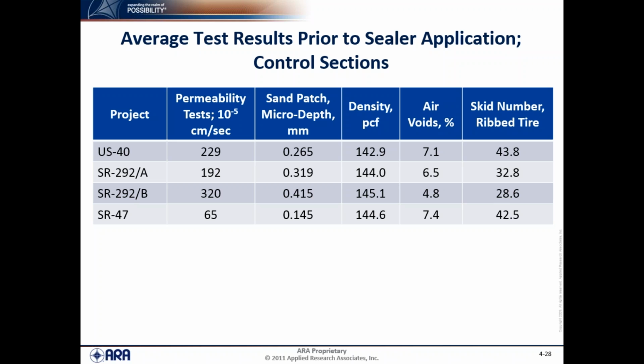So permeability, and you're going to see later on, there was a lot of variability in the water-based field permeability test. And you'll see that in some of the graphs that I'll show later on. But this just shows in terms of 10 to the minus 5 centimeters per second from the water-based field permeability test. The test that we used was the NCAT, or the National Center for Asphalt Technology field permeability test that was developed, and that some agencies picked up and have been using on a day-to-day basis.